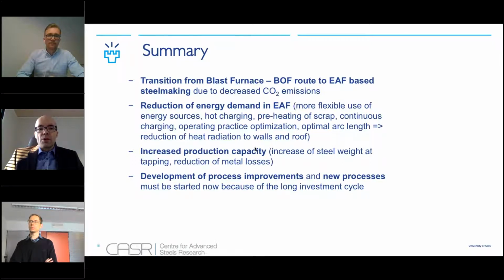And if you look at the reduction of energy demand in electric arc furnace, it is possible to make it by having more flexibility for the energy sources, to use hot charging, to preheat scrap, to have a continuous charging of the scrap for raw materials, with operating practice optimization, or by the optimal arc length, so that we can reduce the heat radiation from the arc to the walls and roof. Of course, increased.